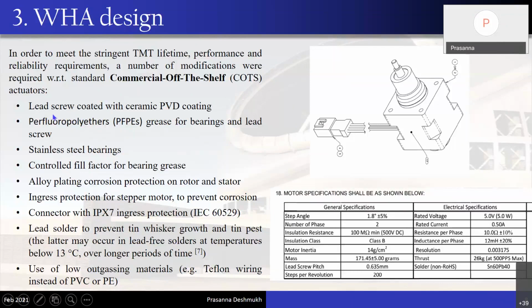One is having a lead screw coated with ceramic PVD coatings to avoid any wear and tear due to repeated operation, and use of grease for the bearings and the lead screw so that there is sufficient lubrication. Use of stainless steel bearings instead of the commercially available bearings, which are corrosion prone. Then a controlled fill factor of the grease within the bearing, because if we have more grease, it will leak out, and that is a problem during vacuum exposure. Then alloy plating on the inside part of the stator and rotor for corrosion resistance, because the conventionally used nickel coating was not sufficient, and we observed significant corrosion.